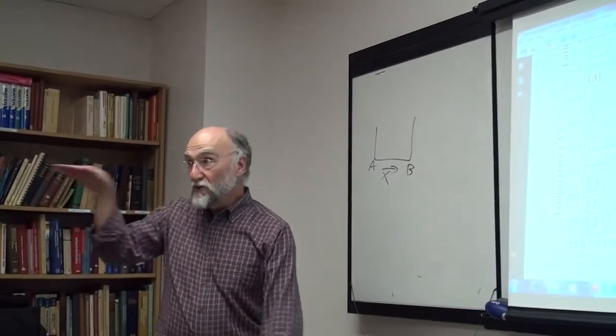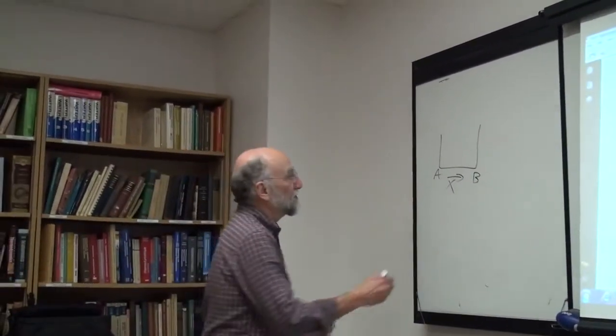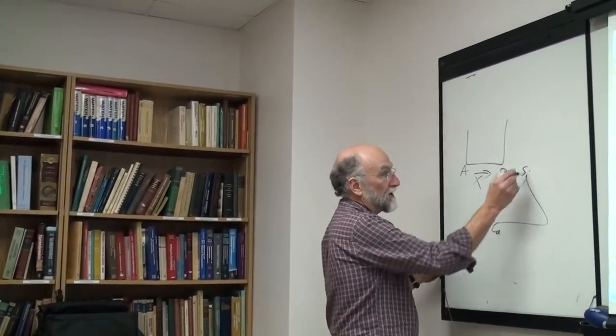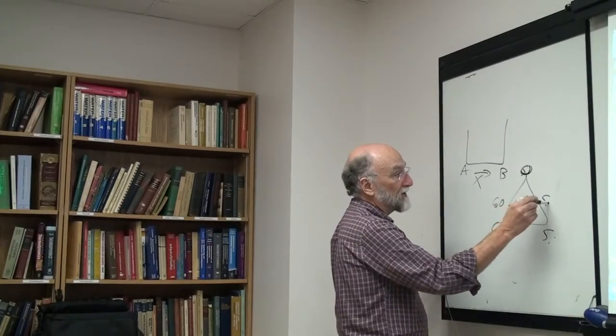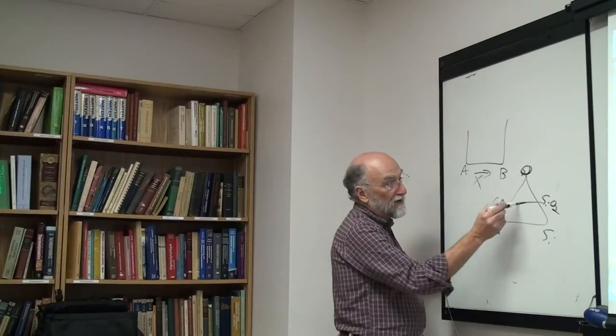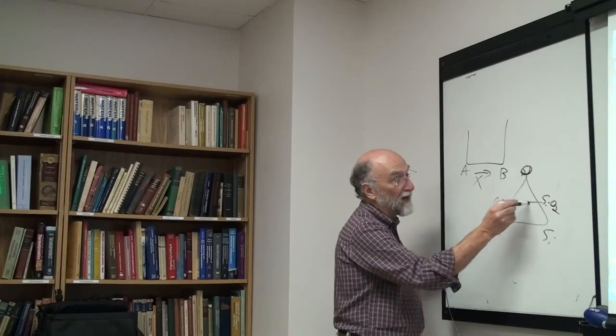Now, there are some cases in which all the tie lines do pretty much lie on the isopleth. I showed the other day, for example, the system calcium, silicon, oxygen, where you go from CaO to SiO2 along this line here. If you have an overall composition here, the two phases, that is the tie line, are going to be along the same line. All your phases are somewhere in the calcium silicates.